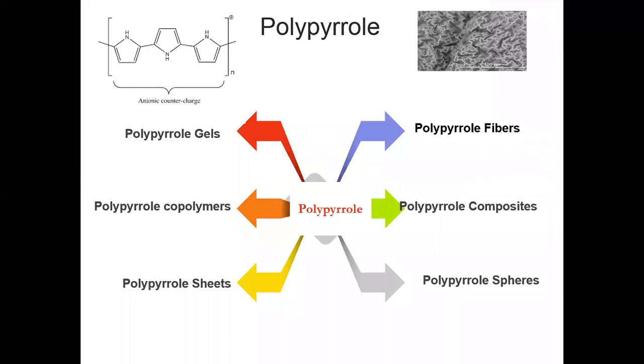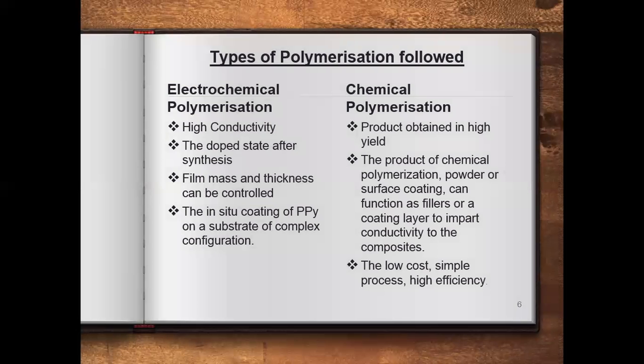The major breakthrough with regard to the routine synthesis of conducting polymers was achieved by Diaz and co-workers when they reported the formation of highly conductive, stable, and manageable polypyrrole films under controlled electrochemical conditions. Later, researchers could develop polypyrrole gels, fibers, copolymers, composites, sheets, spheres, etc. Polypyrrole has been produced by many different methods, which include mainly electrochemical reaction, chemical polymerization reaction, ionic emulsion method, etc. However, for obtaining high yield, chemical synthesis was most preferred. But most of the polypyrrole has been produced by electrochemical reaction because of the high conductivity.